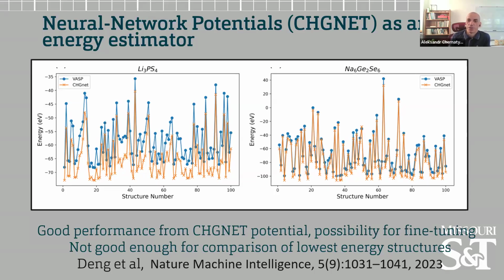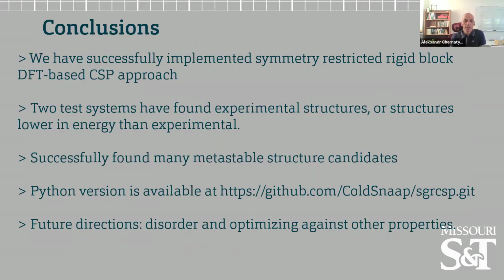CHGNet is not as fast as the classical potentials. It lies somewhere in between as far as its simulation time. And so it is still not ideal, but maybe they will improve. Let me conclude with this. We have successfully implemented a symmetry-restricted rigid block DFT-based crystal structure prediction approach. For the test systems that we have considered, we found all the observed experimental structures, and in some cases we predicted additional ones which might be even lower in energy according to DFT.